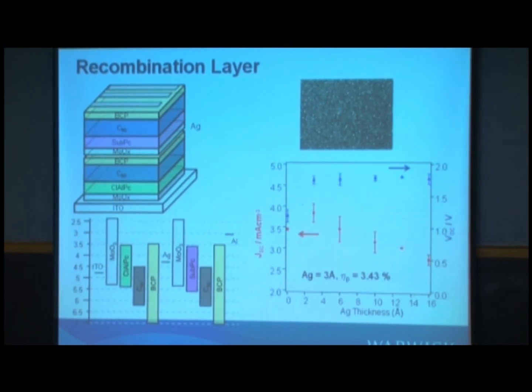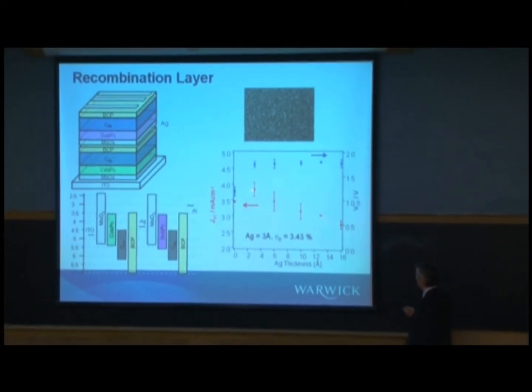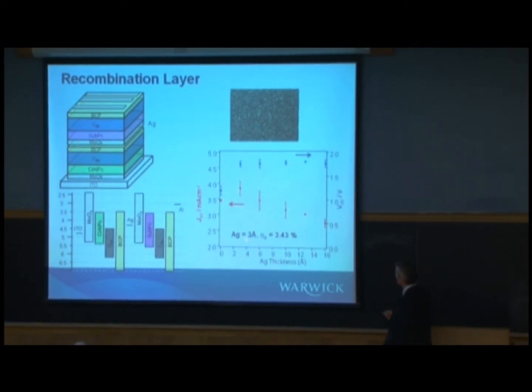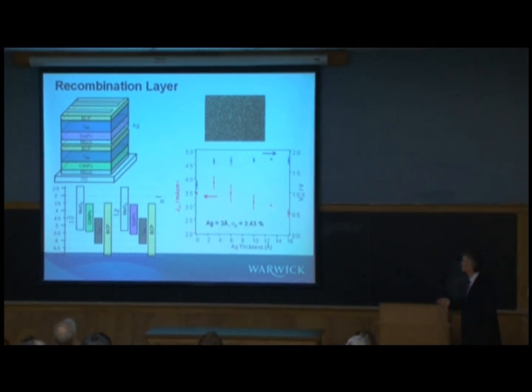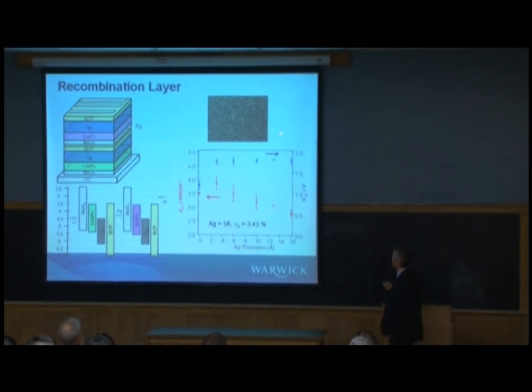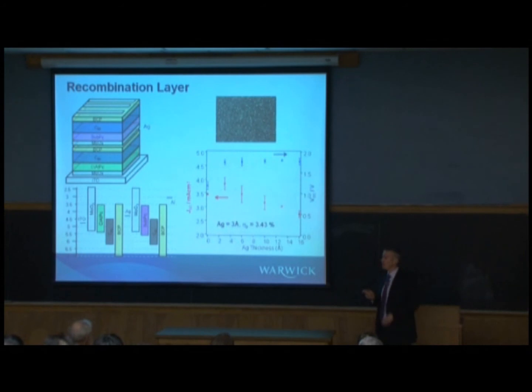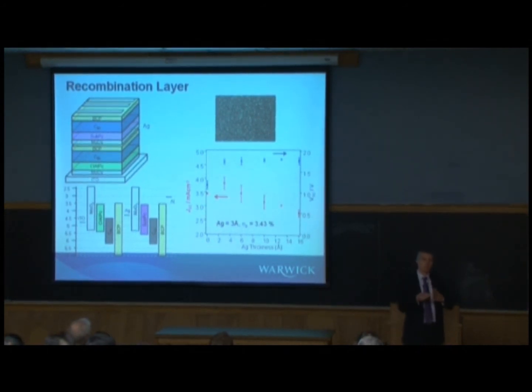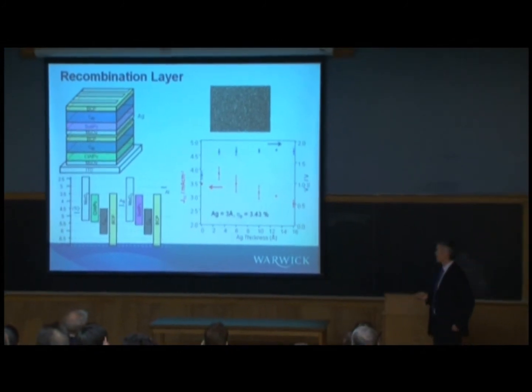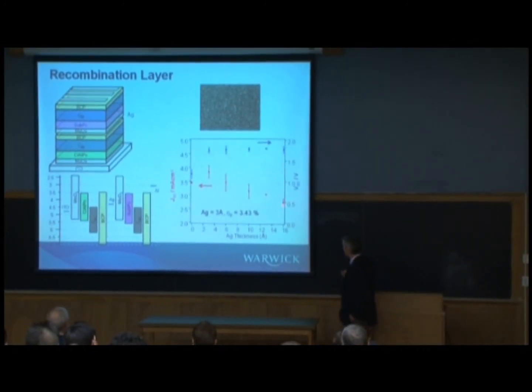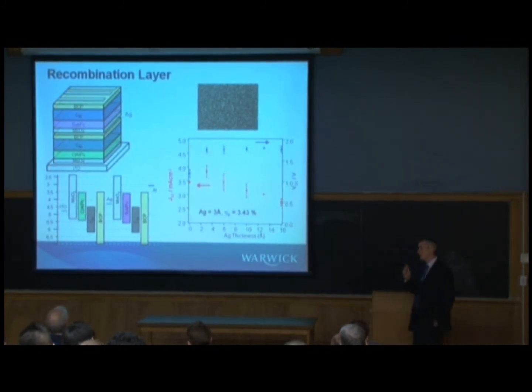So these are nominal thickness. Of course, it doesn't go down as a monolayer. But what you find is that the current here in red maximizes for a nominal thickness of 3 angstroms. And in fact, what happens if you look at the electron micrographs of these materials, it's just silver clusters embedded within the organic matrix. If you have too thick a layer, then of course you're going to lose transparency and so forth, and the device deteriorates quite significantly. But optimizing that recombination layer is critical for balancing the currents in the 2 subcells.